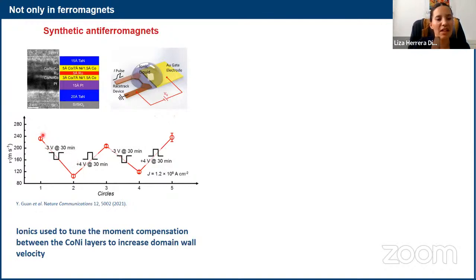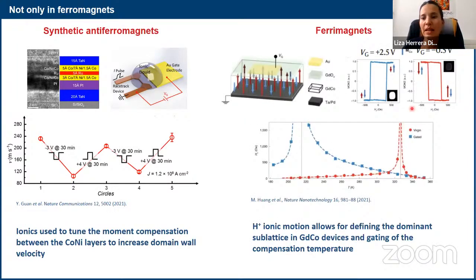So then it's really nice to see variations of hundreds of meters per second, which is very nice. And then this was also shown in ferrimagnets. So this is gadolinium cobalt, and this is once again the MIT group, and they could show nicely that they could go from cobalt dominated to gadolinium dominated